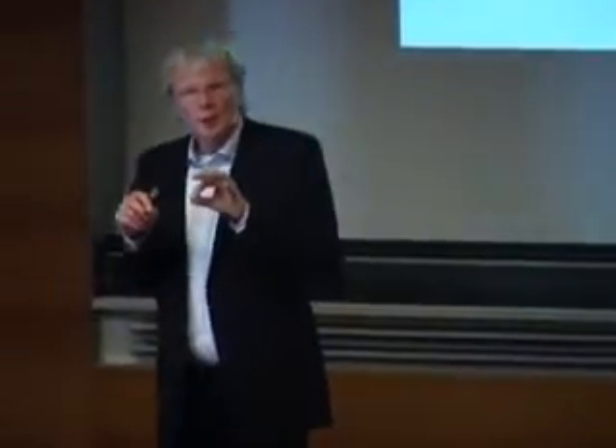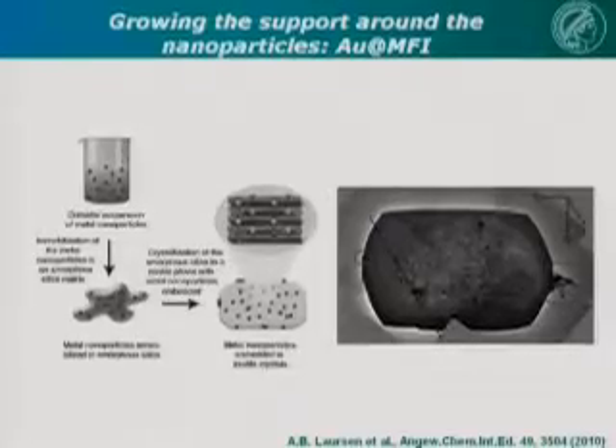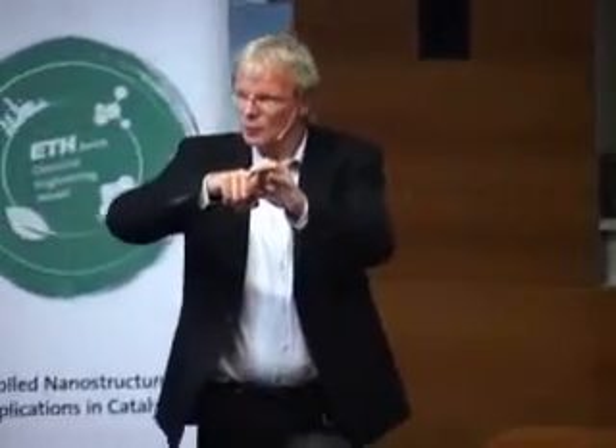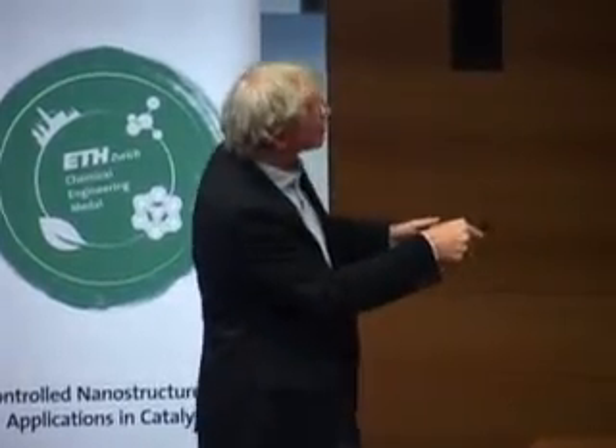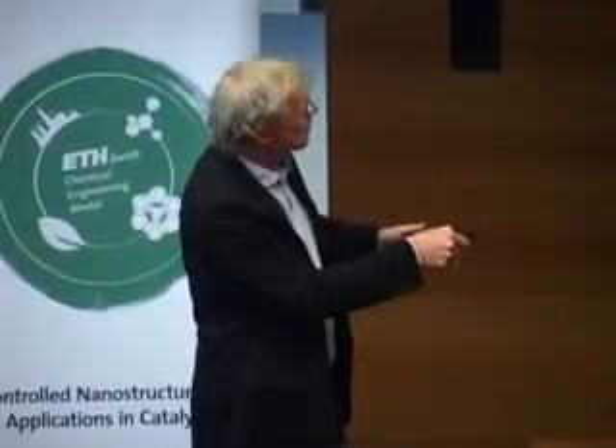There is another possibility of encapsulating catalytic particles in a pore system, and this is something we did with the group in Lyngby, in a cooperation with Søren Kegnæs, for instance. The goal was to put metal nanoparticles, gold nanoparticles in this case, into a zeolite, so that the gold nanoparticles can only be accessed through the pores of the zeolite, through the sharp, narrow pores of the MFI zeolite. So we have gold nanoparticles in the zeolite, but the access to them is only provided through the 5.5 angstrom pores of ZSM-5.